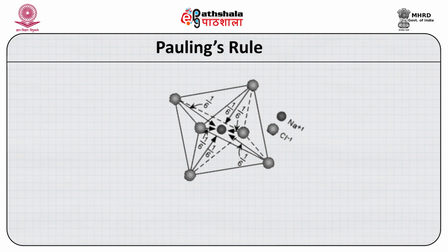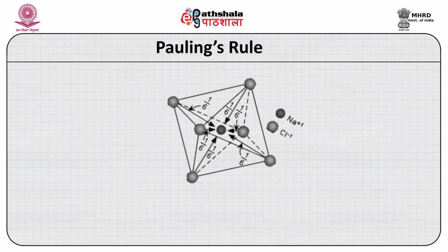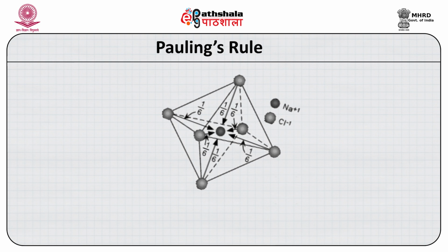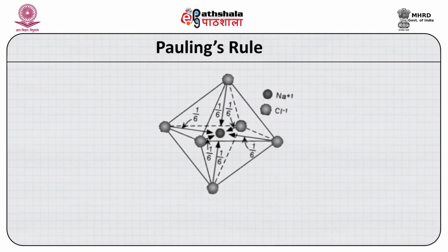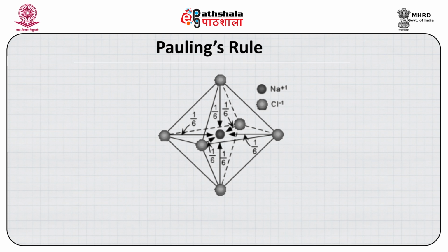In case of NaCl, where the charge is exactly balanced on both the anions and cations, the bonds are of equal strength and they are called isodesmic bonds. In other cases where the bonds are different, that is, the charge is not equally balanced by cations and anions, they are called anisodesmic type of bonds.